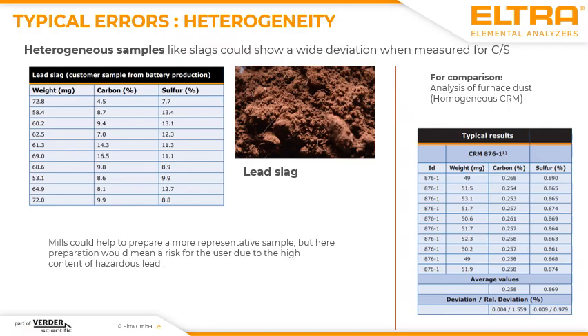16.5%. And it's more or less the same for sulfur, which starts with approximately 7%, but can get up to 12 or 13%. And this is something which could also happen with your sample when you don't know the exact chemical composition and you are facing that maybe this kind of slag or heterogeneous sample can cause such strong deviations. When you only would like to get a rough idea about the chemical composition, then everything is fine and you don't have to do anything more.